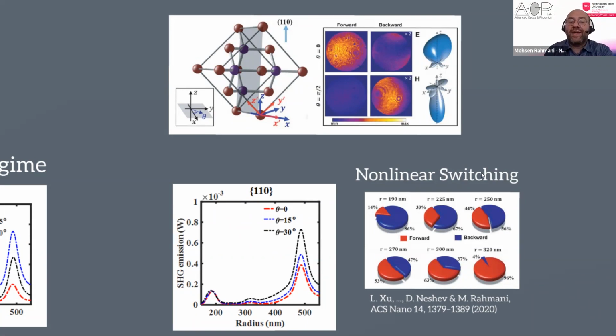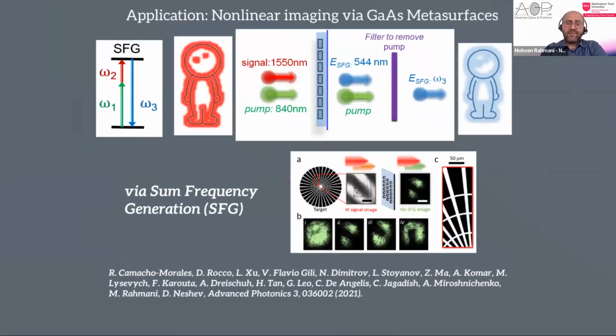And as you see over here, you don't have that problem anymore in the normal. You can have a very nice signal in the normal direction. So by using 110, you don't suffer from that zero emission at 0 degrees or in the normal direction. And as you see over here, only by changing the polarization of the input, you can control the proportion of forward and backward second harmonic generation, which was a very interesting finding a couple of years ago.